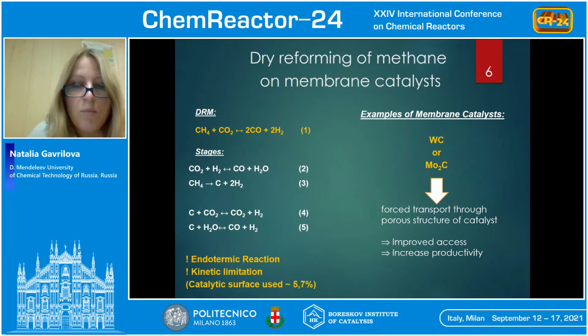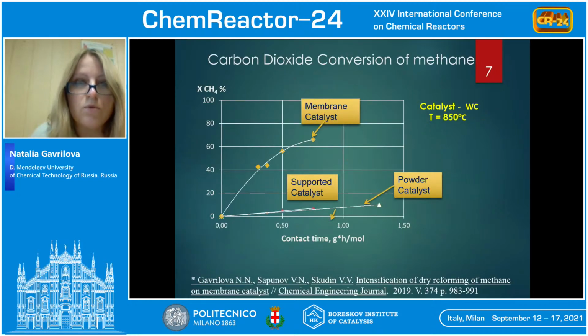In a number of works, it was shown that the use even of a reactor contactor with porous membrane catalysts in the reaction of dry reforming of methane can significantly increase the productivity compared to conventional ones. In our previous work, it was found that the activity of membrane catalysts in dry reforming is several times higher than the activity of traditional catalyst in a fixed bed reactor. These results were explained by the possibility of the Knudsen mass transfer mechanism appearing in the porous structure of membrane catalysts.